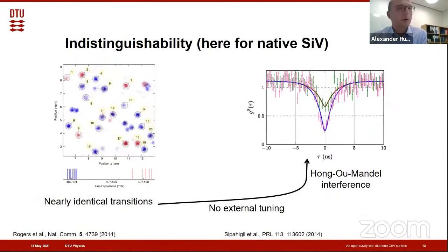Then another feature I wanted to highlight is the possibility to measure indistinguishable photons from such a system. This is a result I took from the group of Fedor Jelezko at Ulm University, and it is representative for native silicon vacancy centers. What I have done here is to grow a diamond and, during growth, dope the diamond with silicon. So it spontaneously forms silicon vacancy centers. That is the way you obtain single color centers